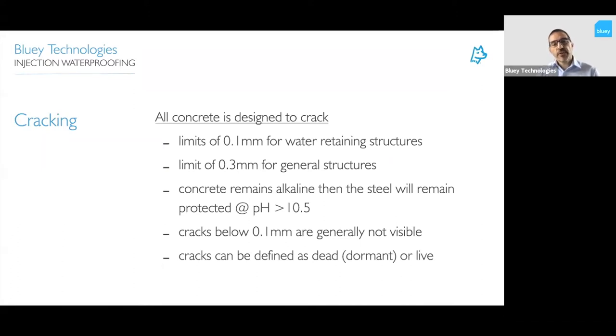And even though you've got that crack there, you're still maintaining an alkaline environment within that crack and around the steel. And you end up with that steel being protected from corrosion because of that alkaline environment. And as long as the pH remains above about 10.5 or thereabouts, then the steel won't corrode. And as long as we're not replenishing oxygen and water into that crack, then the steel won't corrode. Cracks below 0.1 millimeter width are generally not visible. That's an important thing to recognize.